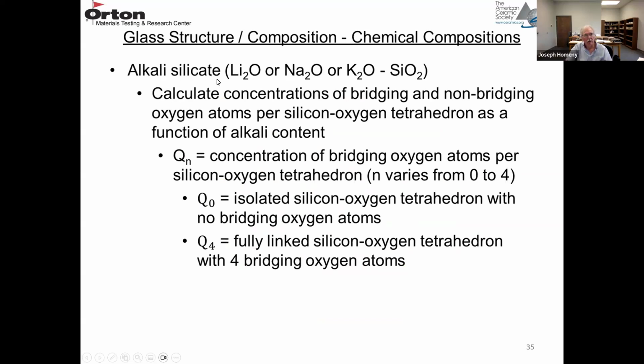So in the alkali silicate glasses, whether it's based on lithium, sodium, or potassium additions, you can calculate the concentration of bridging and non-bridging oxygens per silicon oxygen tetrahedron as a function of these alkali contents. So Q sub n is the concentration of bridging oxygen atoms per silicon oxygen tetrahedron. So n can only vary from 0 to 4. If it's Q0, you have an isolated silicon oxygen tetrahedron with no bridging oxygen atoms. If it's Q sub 4, it's a fully linked silicon oxygen tetrahedron with 4 bridging oxygen atoms. So this would be for your pure SiO2 glass. And then if it's from 0 to 3, it's where you have created some non-bridging oxygens.